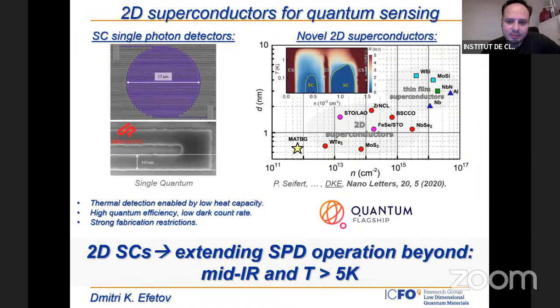And heat capacity is proportional to the amount of carriers, so it's proportional to the amount of particles it shares its energy with. In this regard, graphene is almost the ideal platform for such detectors because it's the thinnest superconductor by far, and it's also by far the superconductor with the lowest electron concentration, and therefore the lowest heat capacity. We have a paper published in Nano Letters where we discuss such detectors, and we find that these detectors could work in the terahertz and even the gigahertz range, at least theoretically.